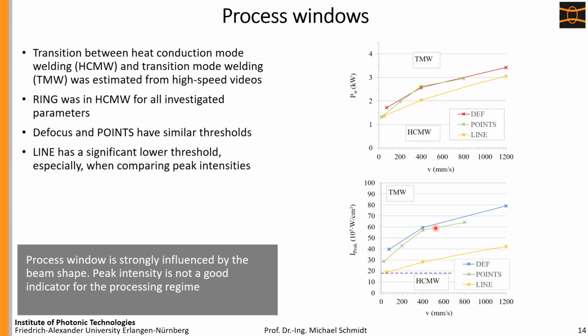Defocus and the pointed line, the point line, have quite similar thresholds, whereas the line has a significantly lower threshold, especially when we compare the peak intensities, not only the power. For the ring shape, you might wonder why you don't see it here. This is because for the ring shape we were not able to leave heat conduction mode. So with the ring shape we never came into transition mode. You might have estimated this because it has the lowest intensity of all of them.